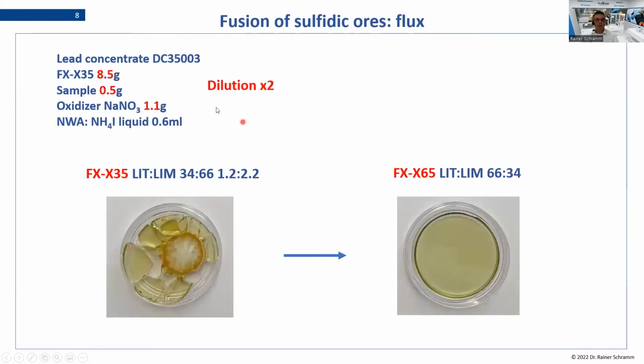Second example, same recipe, but higher dilution. You can see it in the color, how it gets lighter. It's already getting better, the glass. Crystallization in these parts has disappeared, but still cracking not yet perfect. So this would need some more optimization. This recipe with that flux is just working. So you see the band where this is giving a good glass is very narrow, while here this is a much better, more flexible flux. You can use it with more recipes.